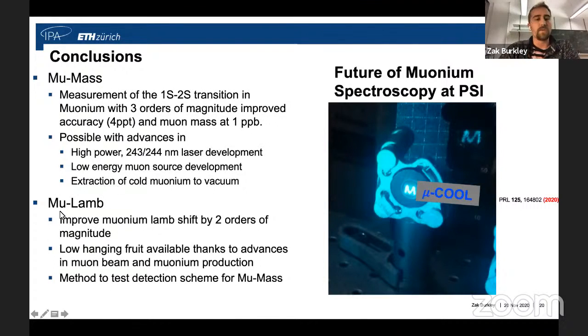And as well, along the way, we'd like to improve the muonium Lamb shift measurement. This is kind of low-hanging fruit thanks to the advances in muon beam and muonium production, and goes along very well with our methods to detect for our MuMass detection. And kind of the future of muonium spectroscopy at PSI is they're developing this muCool system that will give an increase in a couple orders of magnitude of low energy muons, which would be a real game changer in terms of statistics.